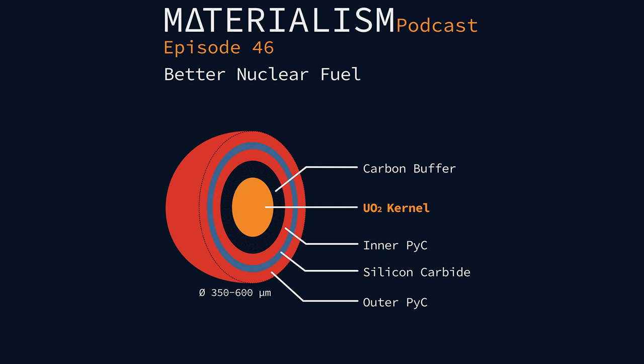And then surrounding that, we have a porous, 50% of its theoretical density, pyrolytic carbon buffer layer. Why is it porous? Why do they need that? Because during the nuclear reactions that occur, we're going to get a lot of new products that are released. There's about 30 different chemical species that get produced when you have a fission reaction, and 25% of those are gases. I gotcha. And so you're going to get swelling. Mm-hmm. Yeah, okay. And so porous carbon is both pretty mechanically compliant. If you start swelling into it, it will give way. But the pores also allow it to trap gases that get sent out from the reaction.